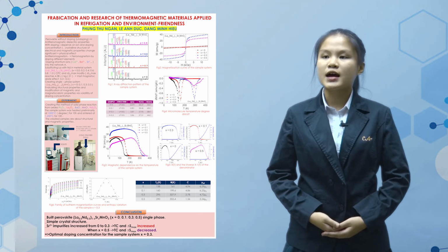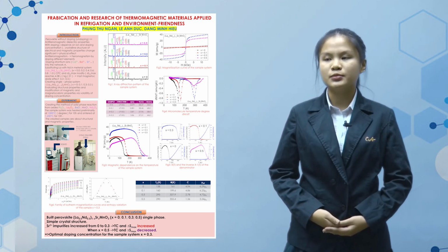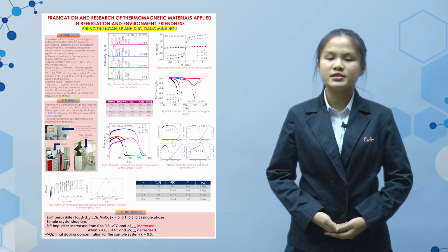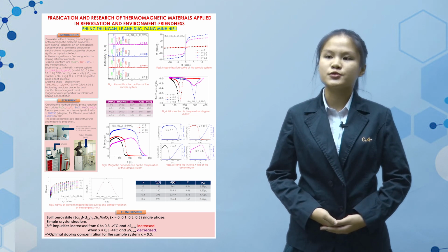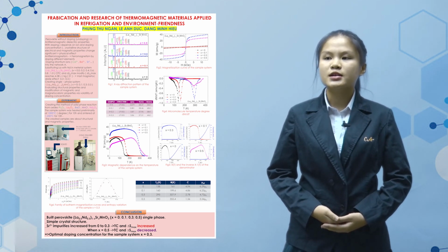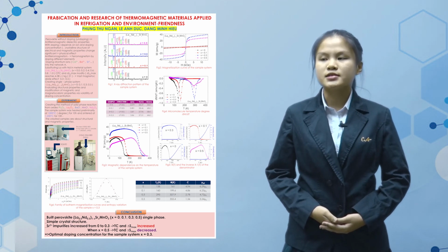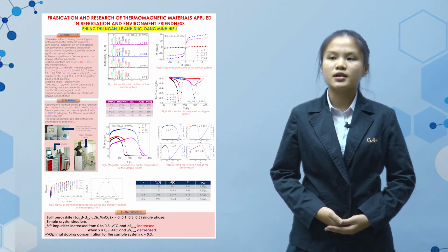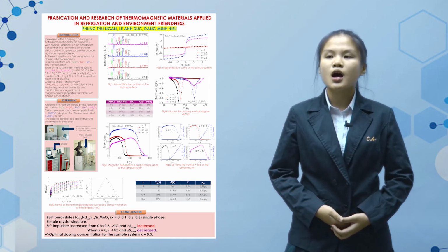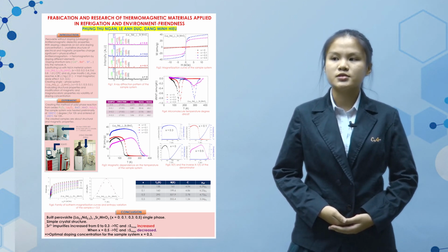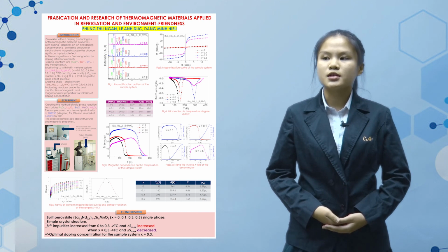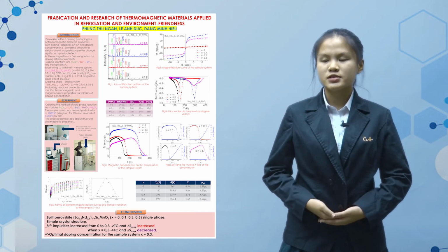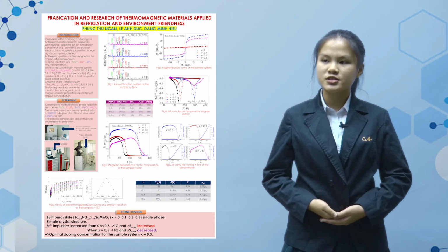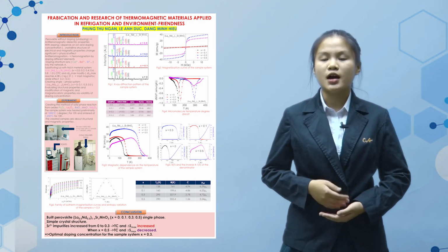Finally, I would like to conclude that we have succeeded in preparing perovskite single phase with a simple cubic crystal structure. Sr2+ impurities increase from 0 to 0.3, Tc and delta Sm increase. When x is greater than 0.3, Tc and delta Sm decrease. The optimal doping concentration of the sample system is x equals 0.3. Furthermore, the materials can be applied in refrigeration, are environment friendly, and have high economic value.